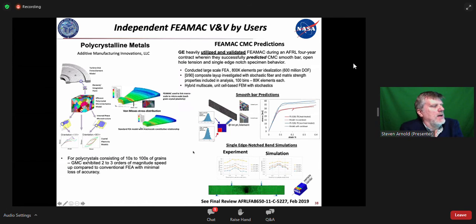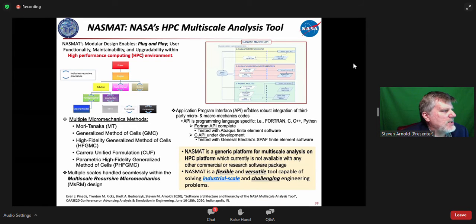Also, we've had a variety of our users provide us feedback on their verification and validation activities. Two notable ones here were Additive Manufacturing Innovation Company, where they were looking at tailoring the microstructure of turbine discs. And then GE, I think they probably have been the heaviest users of our code, and they told us about a 4-year AFRL study that they did, where they were able to successfully predict CMC smooth bar, open hole tension, and single edge notch specimen behavior using our tool set. And you might notice here, too, they were getting up into 600 million degrees of freedom problems, and obviously this would take a very long time on a single CPU, and this was one of the impetuses that we had for developing NASMAT. And NASMAT is our HPC multiscale analysis tool.